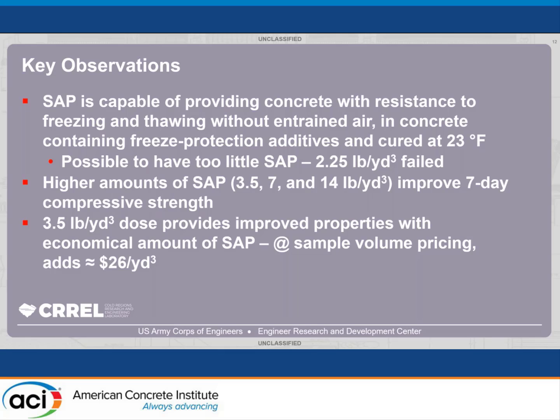So as you're learning about this, you may be interested in, what's the cost? When we did this study, it was a very small laboratory study, so we got a small sample volume pricing. For adding 3.5 pounds per yard, it would add about $26 per yard of your concrete, which, as I said, was sample volume pricing. If you wanted to go larger, it could be cheaper.